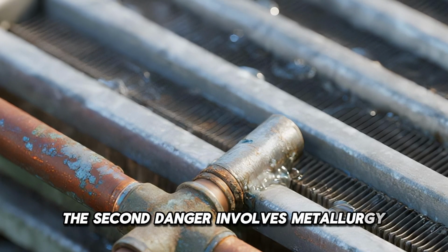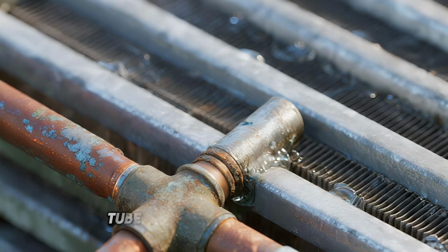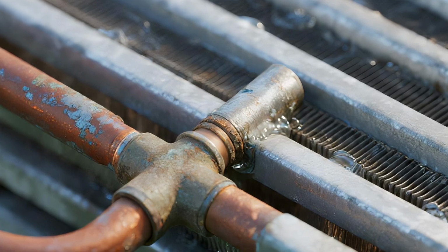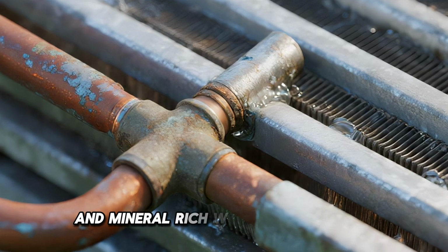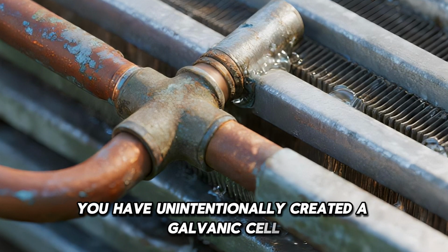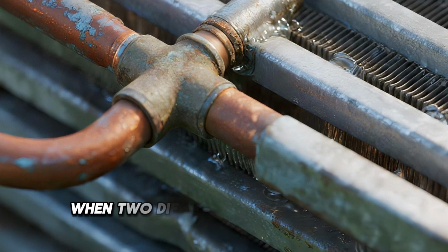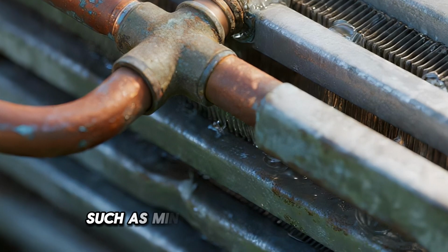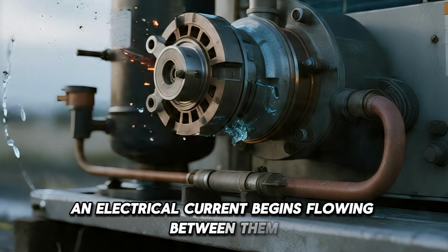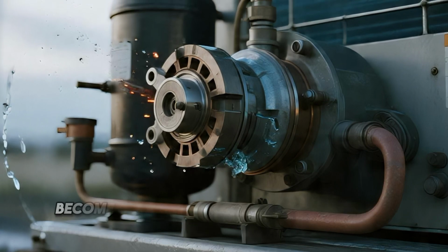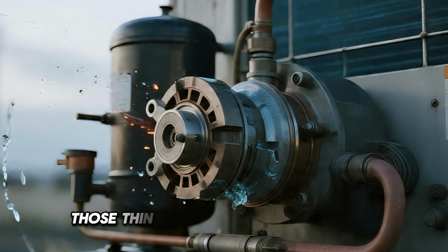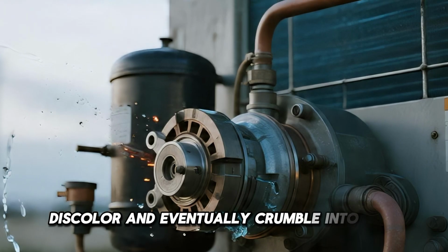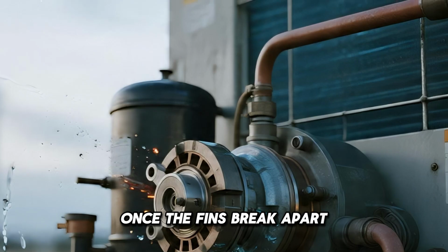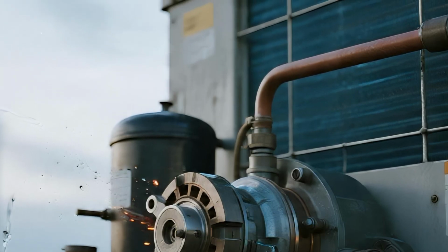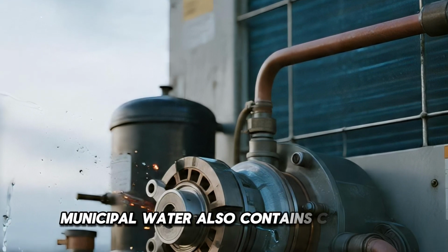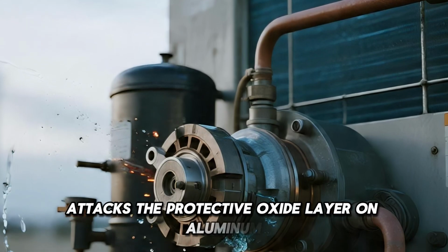The second danger involves metallurgy and galvanic corrosion. The outdoor condenser contains copper tubes surrounded by delicate, extremely thin aluminum fins. When copper tubing is placed directly against aluminum and mineral-rich water is introduced, you have unintentionally created a galvanic cell, a primitive battery. In galvanic chemistry, when two different metals come into contact in the presence of an electrolyte, such as mineral-containing water, an electrical current begins flowing between them. The less noble metal, which in this case is aluminum, becomes the sacrificial anode and starts dissolving. Those thin aluminum fins can corrode, discolor, and eventually crumble into dust within a matter of months. Once the fins break apart, the condenser loses the large surface area it needs to release heat, and the air conditioner is ruined.